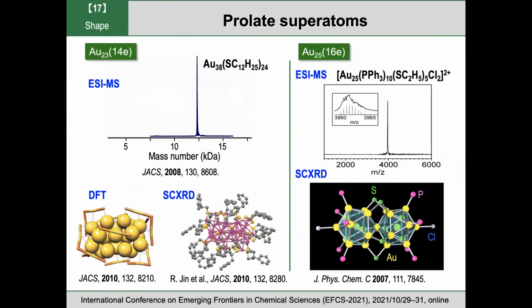The first one is Au38(SR)24. This is a mass spec. You can see the purity of the sample, and the theoretical prediction and the single crystal XRD data appear nearly the same. Both results show that the core is made of 23 atoms, and it is composed of 2 icosahedra sharing 3 atoms.